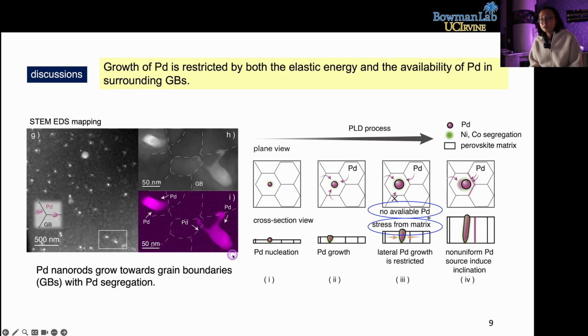So in addition to the elastic strain, the palladium nanorod growth is also related to the availability of palladium in the surroundings. For example, the grain boundary will show palladium segregation. They may diffuse to this palladium nanorod, so that when we see the TEM image and the EDS mapping, we may not find the palladium growing exactly vertically. They may just make some inclined growth, close to the boundary where the palladium is segregated. So both the lattice strain and the availability of palladium contribute to the morphology of this palladium nanorod in the thin film.